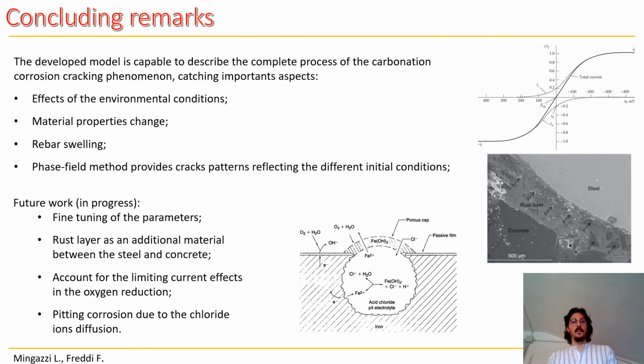Lastly, some concluding remarks on the developed model, which is capable of describing the complete process of the carbonation-corrosion-cracking phenomenon, and it captures also important aspects. For example, the effects of different environmental conditions. It accounts for different material property changes due to the carbonation process. The rebar swelling is obtained as a function of the corrosion current density, and it is used as a loading parameter to obtain the solution of the displacement and damage field. And the phase-field method allows us to obtain crack patterns which actively reflect the different environmental conditions we set for the problem.